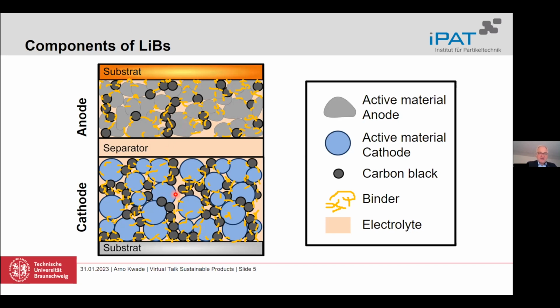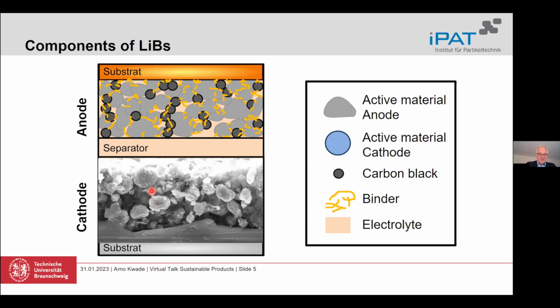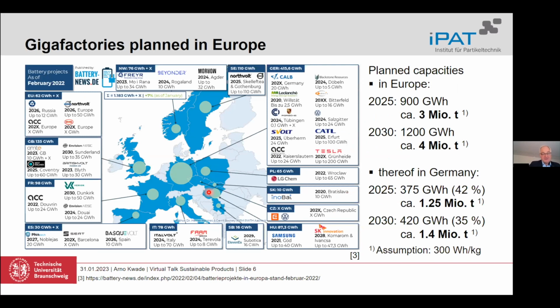And besides the active material particles, which are graphite and these metal particles or metal oxide particles, we have some carbon additives which are important for the electrical conductivity, some binder and so on. And as you see here, these electrodes are composed of particles. So these particles have to be processed, they have to be synthesized, they have to be recycled. And to give you an overview of what it means regarding mass, the amount of particles: if we get all these factories which are planned in Europe today, you see that in 2025 we already talk about 3 million tons of these materials, and in 2030 about 4 million tons. So this is a really huge amount, and it's also in Germany still a really big number.